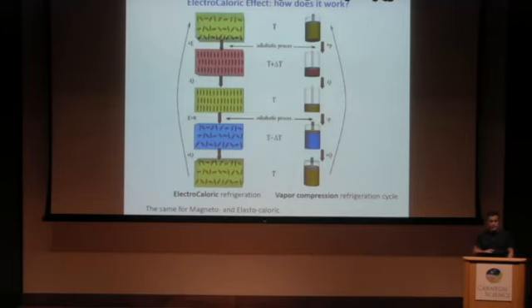So this slide has been more or less described by Andrew just before. The idea actually is to play with the order and disorder. The idea of applying an electric field is to order the dipoles in your system, and once you order these dipoles, if you are working in adiabatic conditions, then you have heating of your system. If you keep this field applied, then you can remove the heat, keeping the dipoles, of course, aligned, and then you switch off the electric field, always in adiabatic conditions, and then you have decreasing of the temperature.